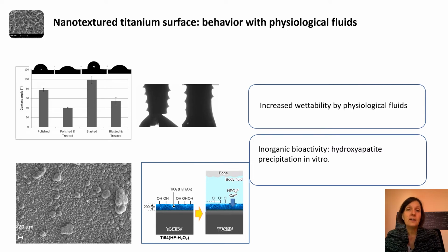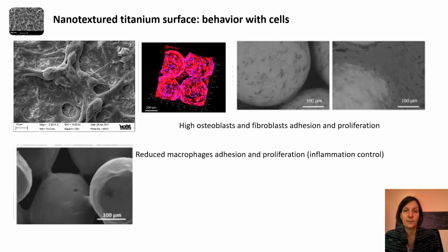And because of this, the surface has a very high wettability, so it is able to attract the physiological liquids. This is a dental implant with this treatment, and you can see that there is an attraction force for the liquid. And we have a bioactivity, that means the ability of inducing precipitation of hydroxyapatite during in vitro tests, and so hopefully also in vivo. You can see here a pretty nice layer of hydroxyapatite on the surface of the treated titanium alloy.